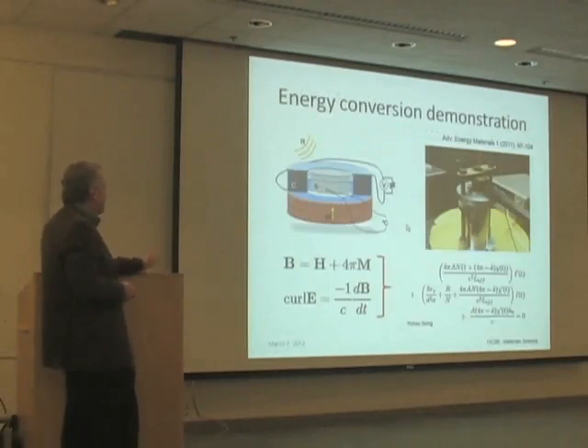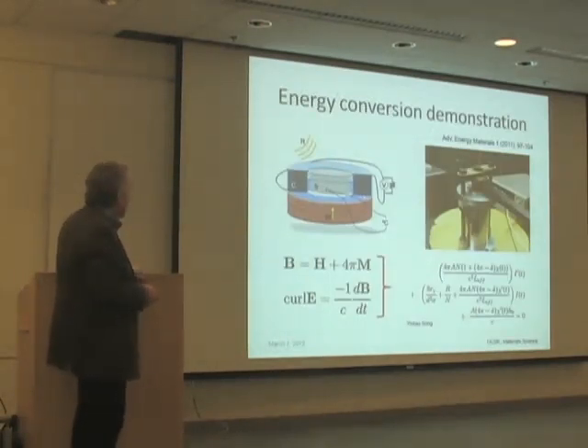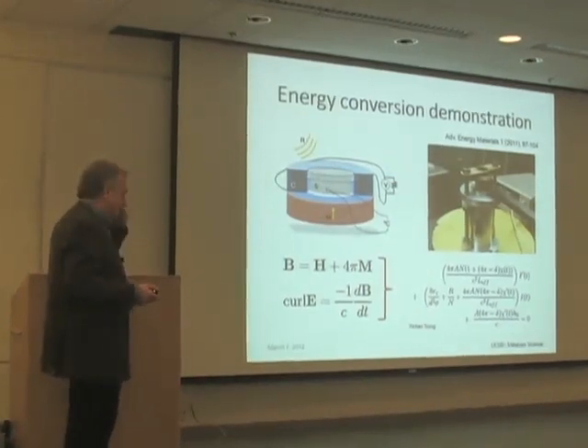Okay, here's something more interesting about energy conversion. So we took a piece of that material, and we put it on top of a permanent magnet. And then we wrapped a coil around it. And then we heated it up. And when we heat it up, it goes through the phase transformation, and it suddenly magnetizes to a big value. So you can think of, in terms of Maxwell's equations, dM/dt is very big. But dM/dt is partitioned between dH/dt and dB/dt. And that partitioning is governed by micromagnetics, or magnetostatics really.